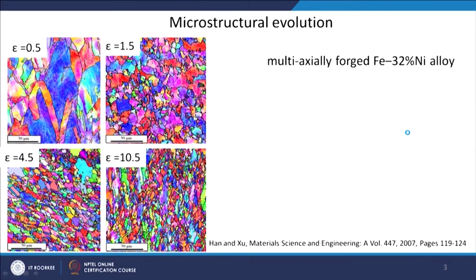Now, this is the microstructural evolution as a function of strain. At 0.5 strain, 1.5 strain, in this way the strain is increasing, and you can see the effect of strain on the grain refinement. Initially the grains are coarse, and of course also look elongated in one direction, and there is some substructure development within the grain also.